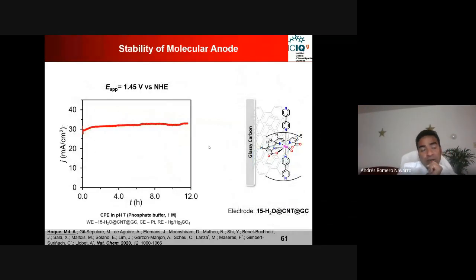And then we thought, okay, let's check the stability, because at the end, ultimately, we want to do this bulk electrolysis to continuously oxidize water molecules in order to get oxygen and then hydrogen. So we take that, and the current density we are getting in this technique is approximately 31 milliamp, and it remained stable over more than 12 hours.